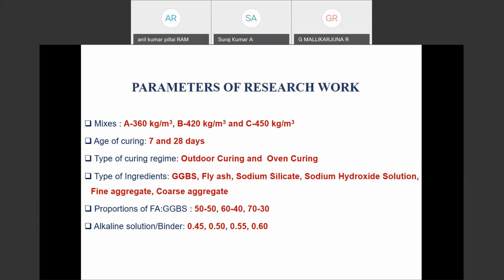Yes, sir. And the type of curing regime we considered was outdoor curing and oven curing. The ingredients we considered were fly ash, GGBS, and sodium hydroxide and sodium silicate solution. The proportions of fly ash and GGBS we considered were 70-30, 60-40, and 50-50. We considered 4 different alkaline to binder ratios.